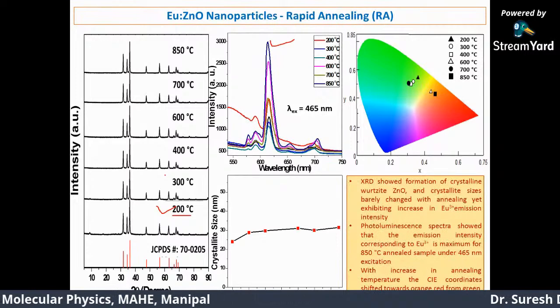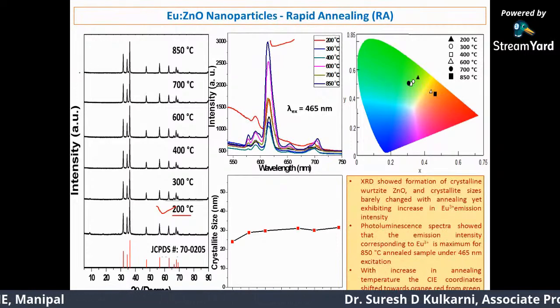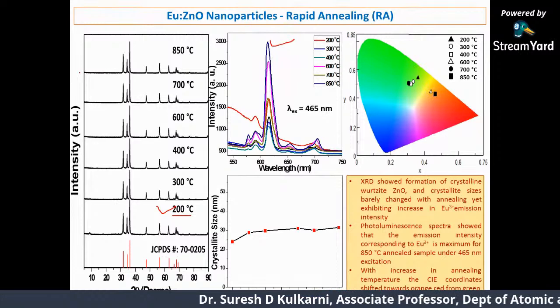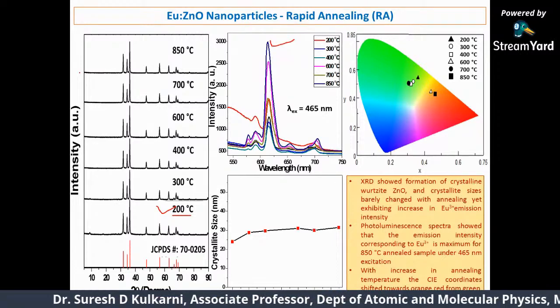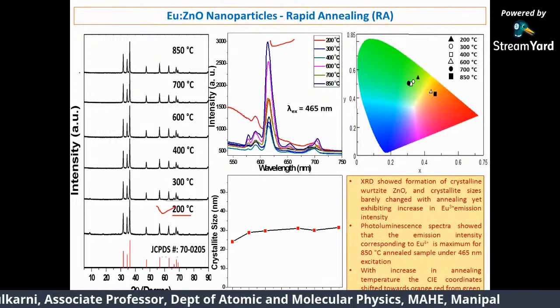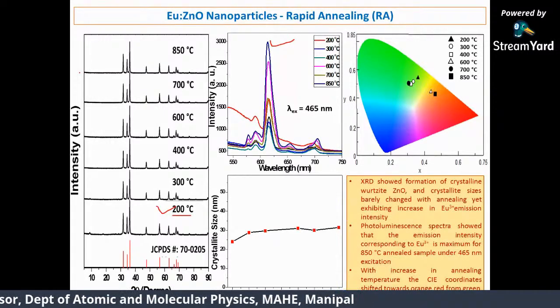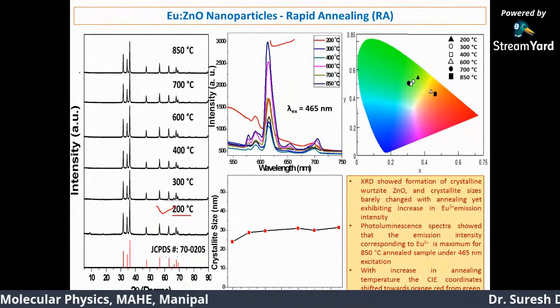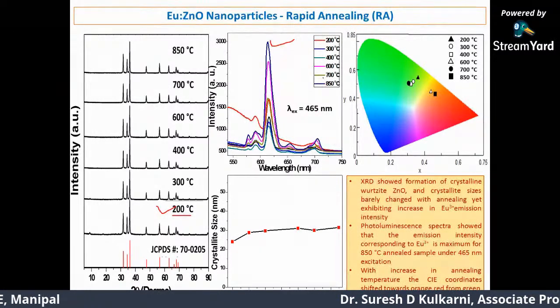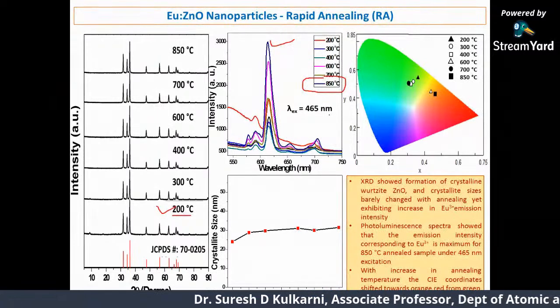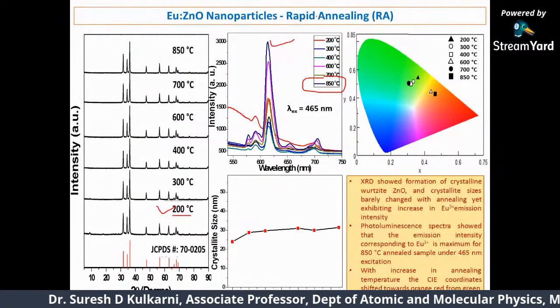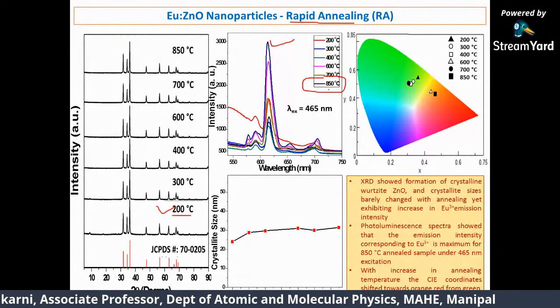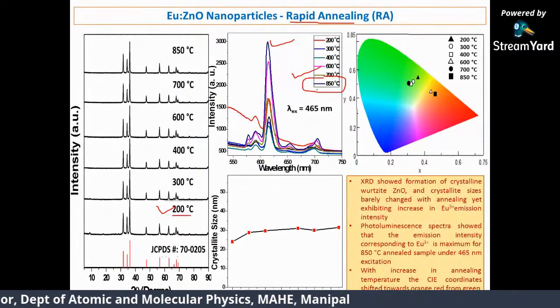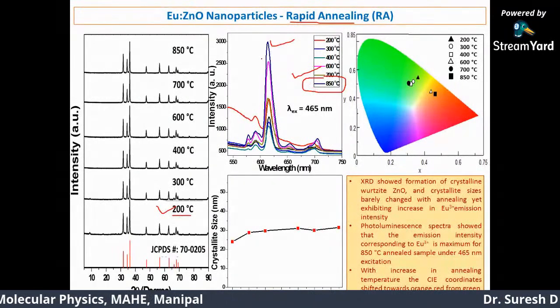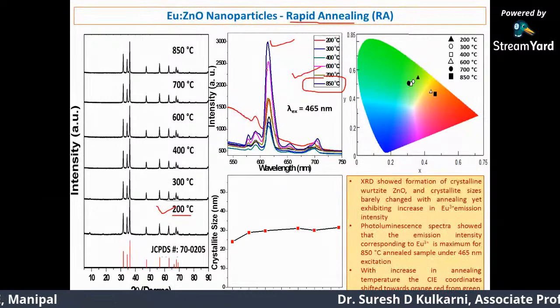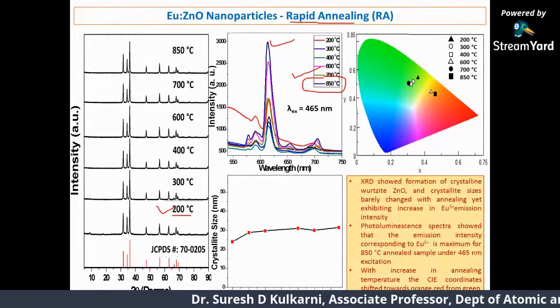It's giving you good optical properties, and these are beneficial because it reduces the processing time. Time is money in industry, and also the quality of the product is going to be much better. Even if I consider here, some of you may be noticing there is mention of 850 degrees Celsius. With a rapid annealing, 850 degrees Celsius can be achieved in about 4 to 5 minutes. Okay, so within 4 to 5 minutes, I have converted a starting material into a technologically useful material.